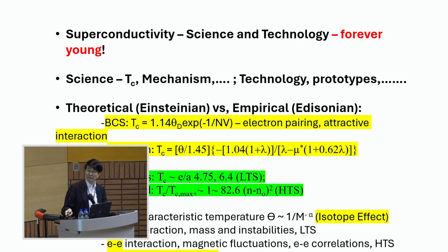And then the electron-phonon interaction, usually, as you can see here, to get higher TC, you like to get this lambda value as big as possible. But once you get it big enough, the lattice becomes unstable, so that's another challenge we're facing, to try to overcome.